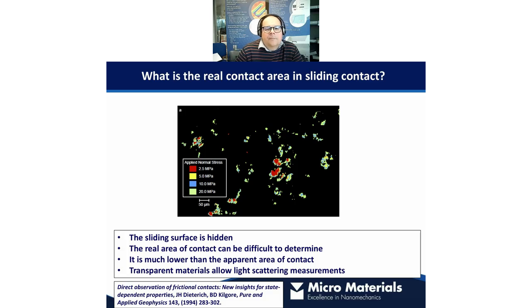So just along the same lines, this is some sort of reflected light observation of two surfaces together. If we imagine the black rectangle there, I don't think you can actually see the cursor as I'm showing the slide, unfortunately, but the black rectangle there is the nominal contact area, and the colored regions, the red and the green, a little bit of yellow, they represent, in terms of a pressure scale, the actual contacts. So you can see that the actual contact is a very, very small proportion of the nominal contact area.